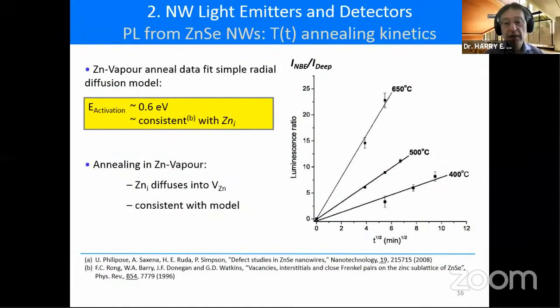we did a time-temperature set of annealing experiments shown on the right here, and we've plotted the ratio of the near band edge to deep emission luminescence, and you can see that we can very nicely fit that using a simple radial indiffusion model for the zinc vapor coming into the wire or leaving the wire through radial diffusion. And all of those curves fit with an activation energy of around 0.6 of an electron volt. And that corresponds exactly to well-known old data on the diffusion coefficient for zinc in zinc selenide. So we can explain everything essentially in that regard.